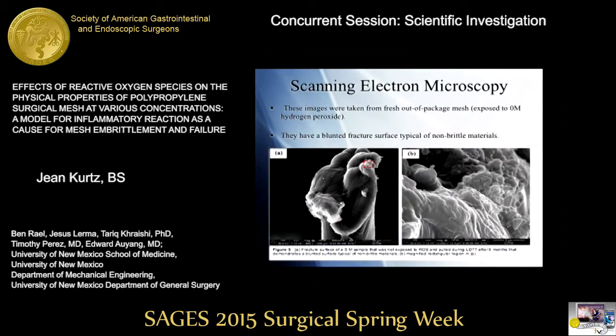So here are the results from our scanning electron microscopy. This is a picture of fresh out of the package mesh that was never exposed to hydrogen peroxide. You'll see that it has a blunted fracture surface. These are the actual ends where the mesh was stretched apart. So if you imagine pulling apart a piece of chewing gum, you'll see a nice rounded edge. This is very common in non-brittle materials.